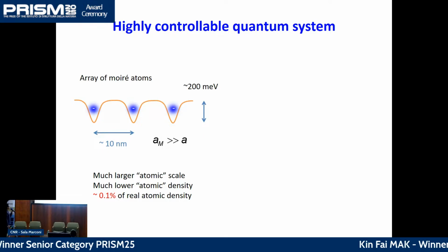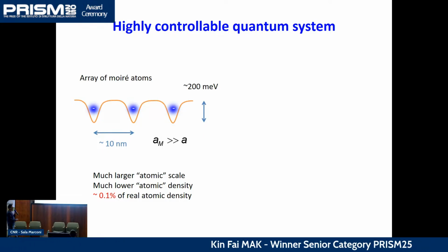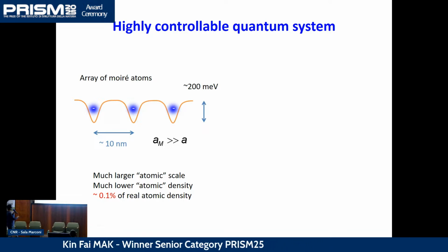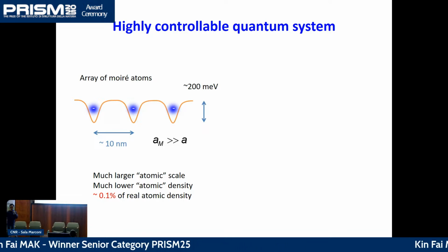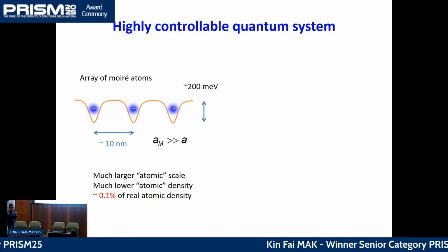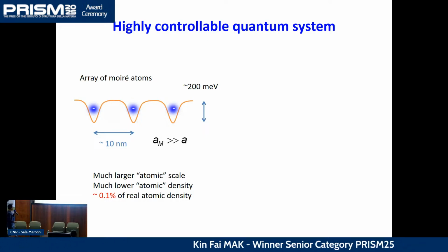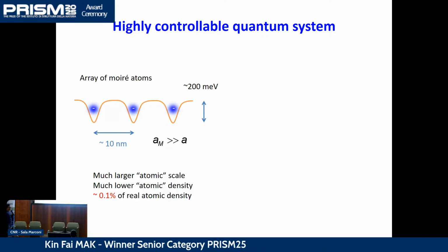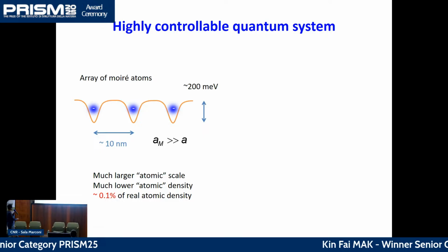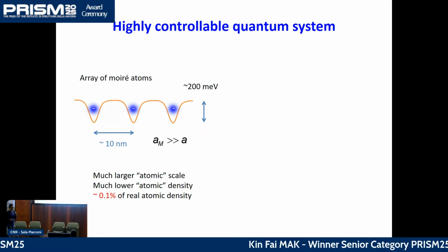Second, the system is highly tunable. You can think of the system the following way: as an array of moire atoms. Now the atoms are no longer angstrom big. Instead, each atom is 10 nanometers big, so they are much bigger artificial atoms. The electrons can be trapped by the potential of this array of artificial atoms. And you can think of this as an artificial material with a density of only about 0.1% of the real atomic density.